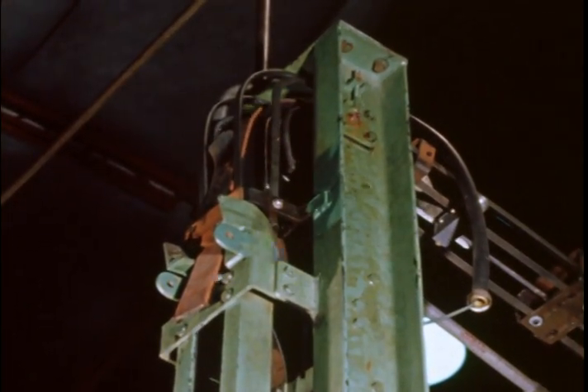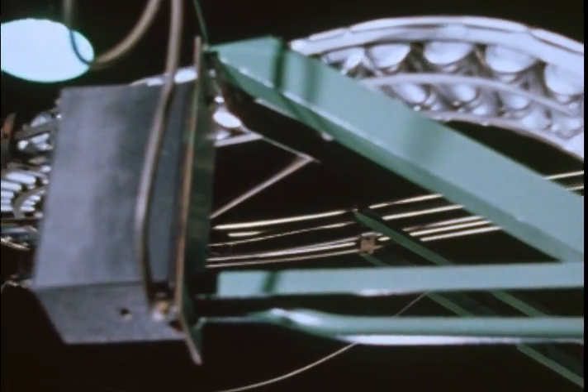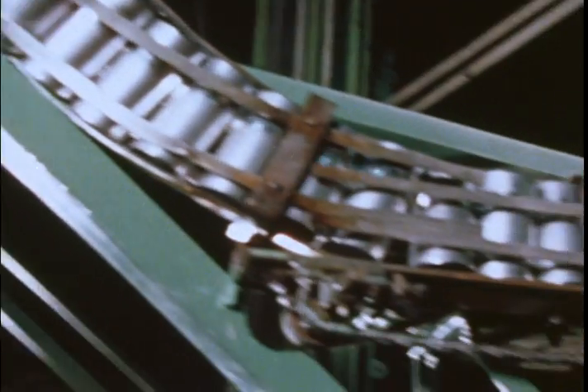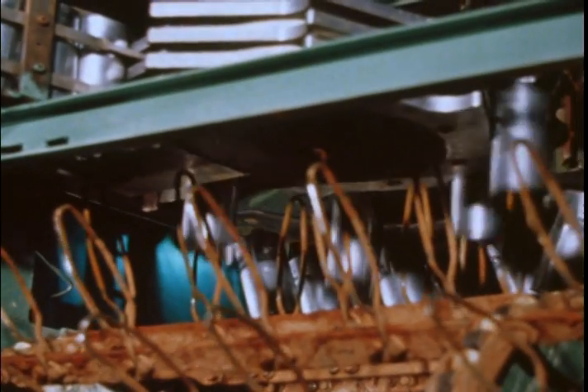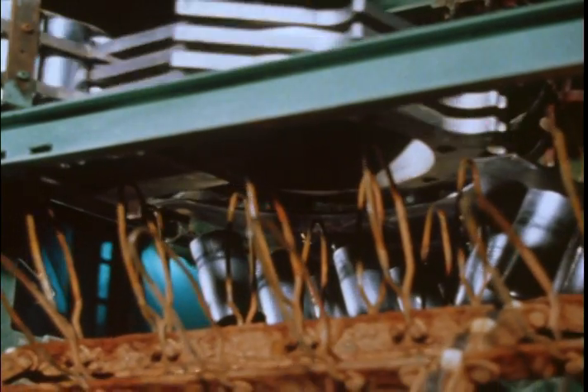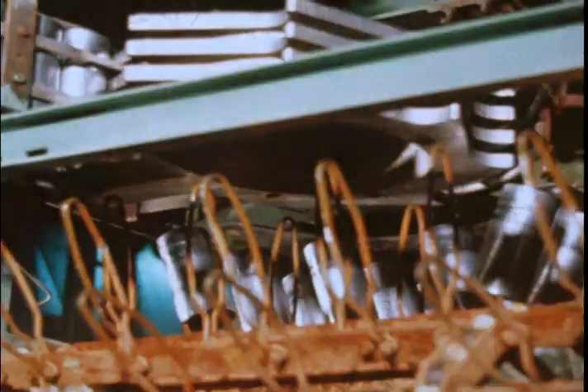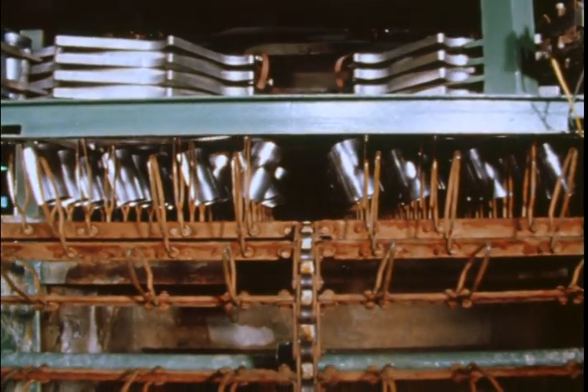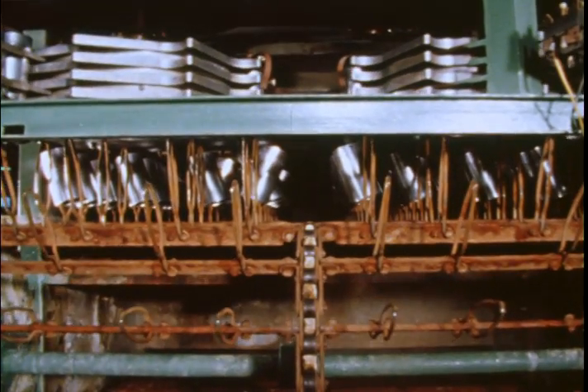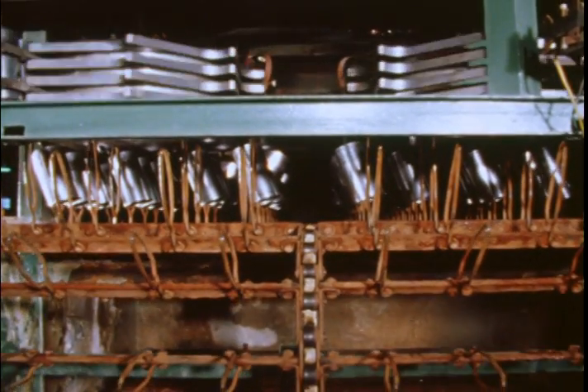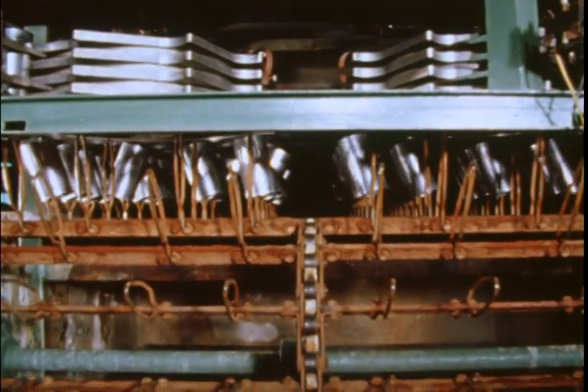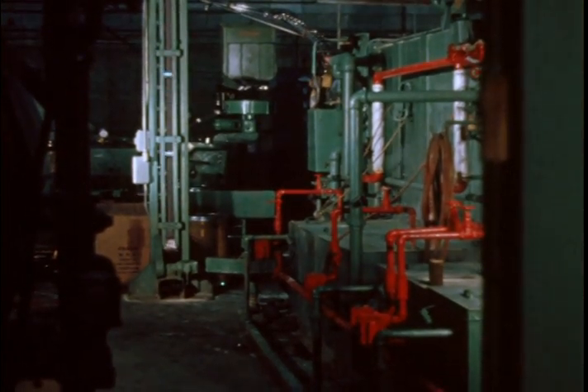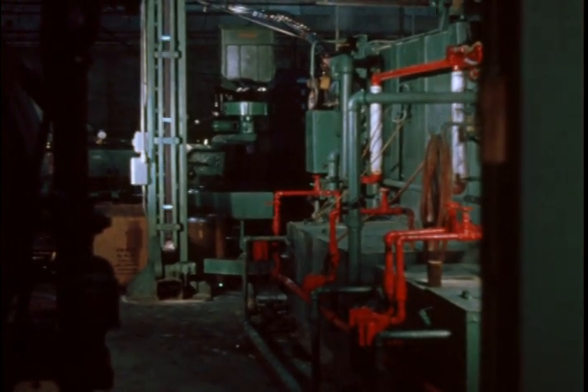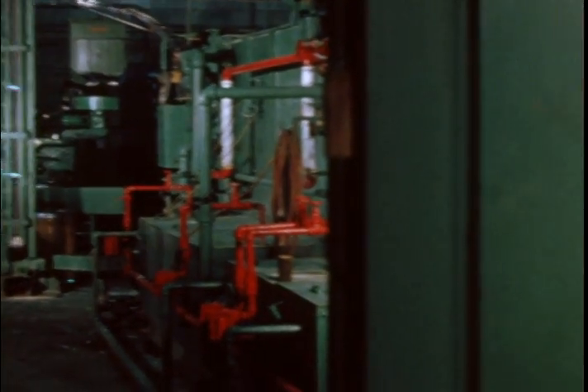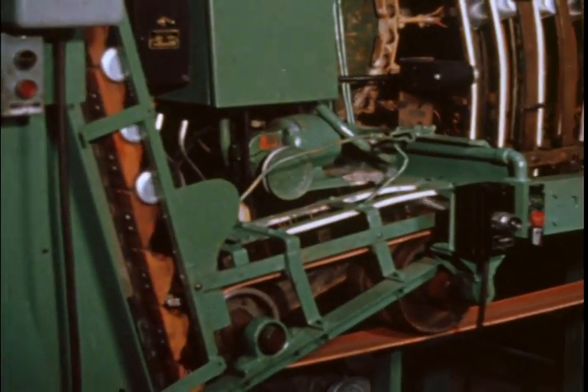After trimming and flanging, and before the decorating and internal lining operation, the cans must be thoroughly degreased and the surface properly prepared by etching so that they will receive the inks and the lacquers. This machine is a washer which performs that function. We are looking down along the side of the washer where the cans enter to the discharge end where the cans are emerging.